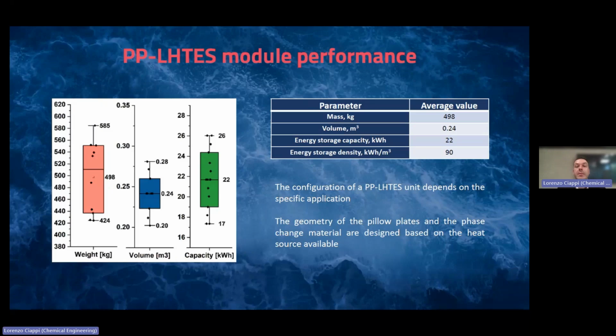The values of the key performance indicators of the entire set of modules considered are reported in this slide. It was found that the average mass of the system is about 500 kilograms, while the average volume of the module is around 0.24 cubic meters, and the energy storage capacity was found to be 22 kilowatt hour, and an average energy storage density is 90 kilowatt hour per cubic meter.